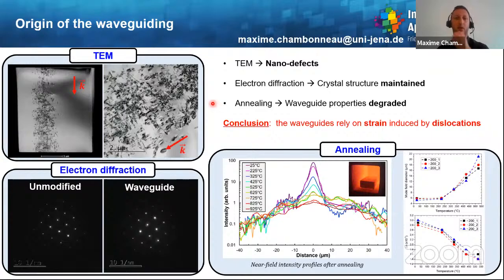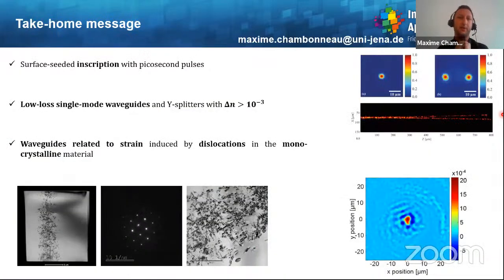Finally, we have carried out recently some annealing experiments, as you can see here. I will not go into the detail, but the main conclusion of those experiments is that when you increase the annealing temperature, the waveguide's properties are degraded, namely the mode field diameter increases, as you can see here on the right, and the refractive index change decreases. So our conclusion is that the waveguides we have written rely on strain induced by dislocations.